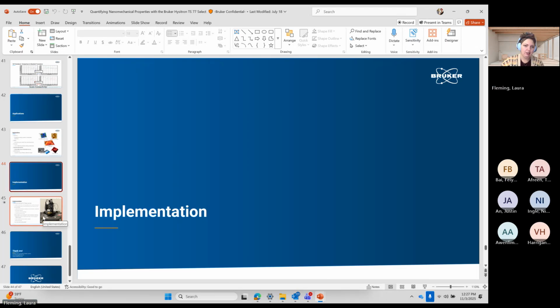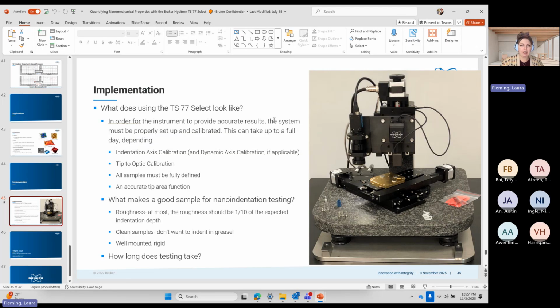Good question. So, implementation of testing. Oops, sorry, one slide too far. I like to answer this question before it gets asked: how long? You walk into an empty instrument and you have a sample in your hands. How long does it take you to get set up to make sure that you can test that sample successfully? The answer is anywhere between 2 hours to 8 hours, depending on how well the system is set up to begin with. Now, for you guys, your system only has that one transducer. Many of my customers have more than one, so they're swapping transducers and probes all the time, which can make the setup take longer.